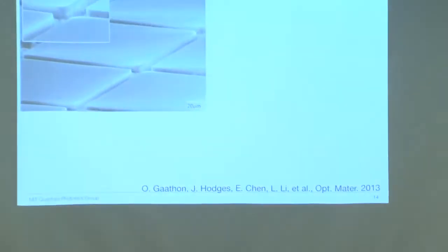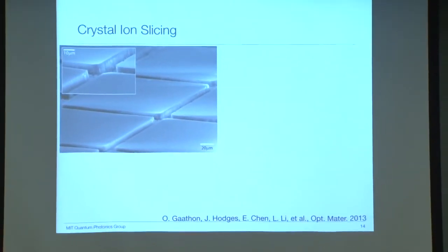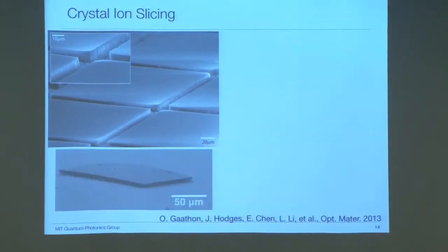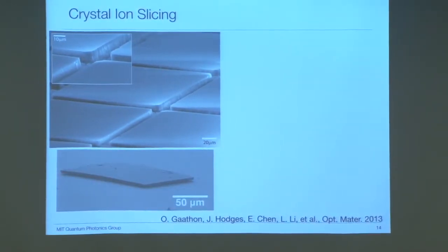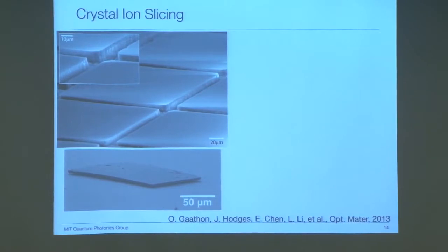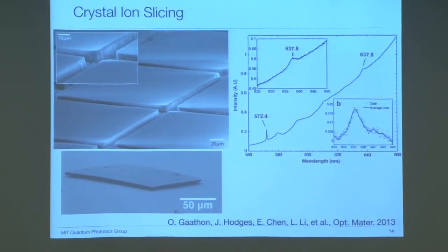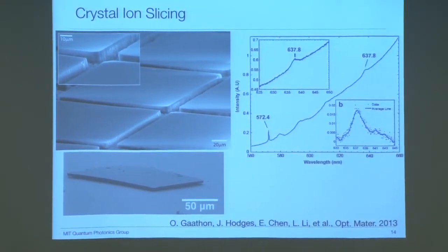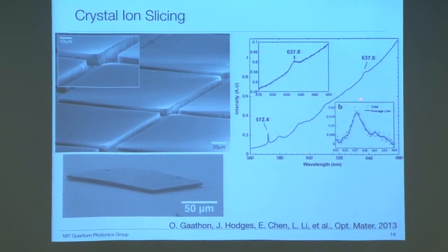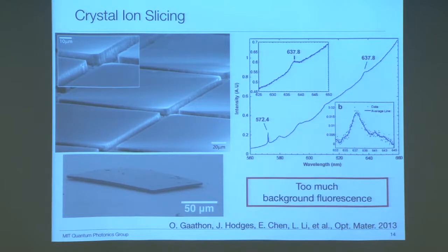And this is a resultant ion sliced diamond membrane still attached to the bulk diamond. And this is a transferred one onto another substrate. And we measured the optical property of this transferred diamond membrane. Turns out that there is NV ZPL, that's good. But the bad news is that there's too much background fluorescence.